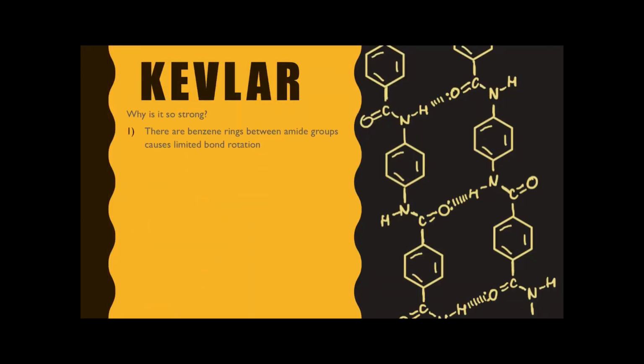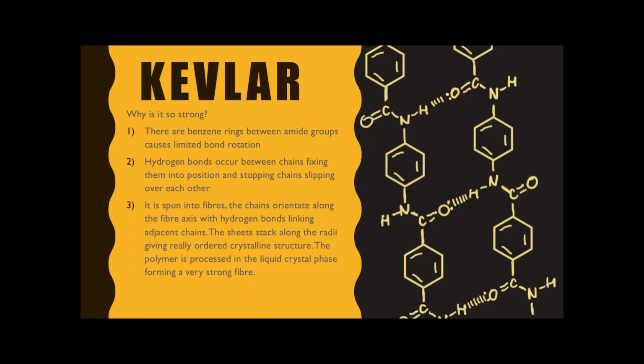This is because there are benzene rings between the amide groups, which causes limited bond rotation. There's also hydrogen bonds that occur between the chains, fixing them into position and stopping chains from slipping over each other. It's spun into fibers and the chains orientate along the fiber axis with the hydrogen bonds linking adjacent chains. The sheets stack along the radii, giving a really ordered crystalline structure, and this polymer is processed in the liquid crystal phase, forming a very strong fiber.